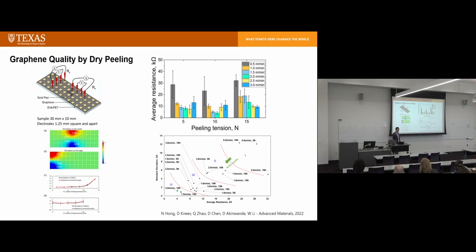But the conductivity we measure in the center and close to the edge are different because of the electric field distribution. So we did a COMSOL simulation. We figured out a correcting factor so that we can correct the edge effect of the measurement. So with that, we took average resistance measurements under different peeling tensions, 5, 10, 15 Newton, and we ran the machine at different peeling speeds. So you see, obviously, the quality of the samples is dependent on the peeling tension and also peeling speed.